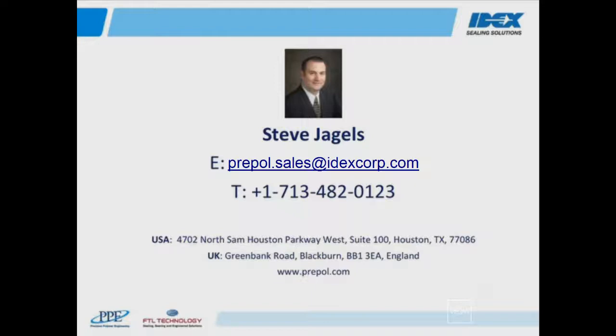What is the maximum level of H2S that a low temperature FFKM can handle? Yeah, that's a great question. We essentially believe that the low temperature perfluoroelastomer FFKM is inert to H2S or sour gas. We have test data showing testing to the NORSOK type protocol, but with the gas composition of 25% H2S, 3% CO2, and 72% methane at temperatures up to 175 degrees, and we've really seen no detrimental effects to the physical properties. So we feel very confident that the low temperature perfluoroelastomer doesn't react with sour gas.